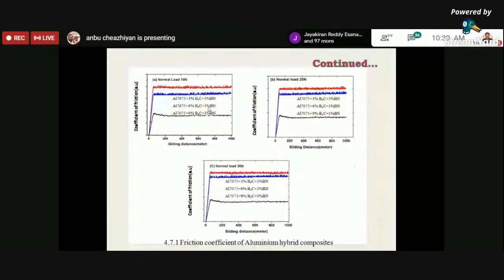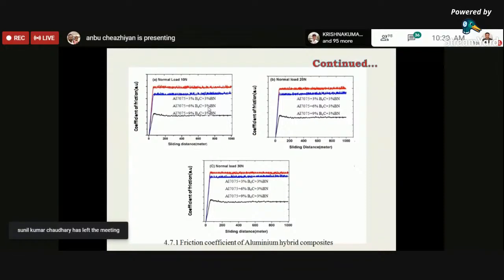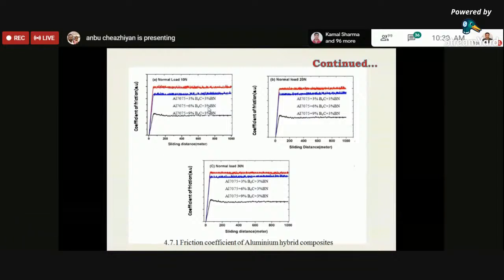The friction coefficient of each material has been increased. So by using that formula, we have calculated the friction as 0.46 to 0.47 for hybrid composites. The coefficient of friction increases due to the strengthening effect of matrix and reinforcement, and also the dislocations in the alloys are ineffective, which causes an increase in hardness, the most important factor to enhance the wear resistance.